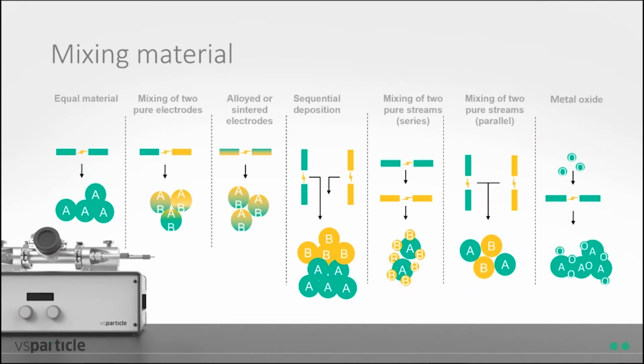Again, there's enormous flexibility also in mixing different compounds. We can use two electrodes of the same material producing the same nanoparticles. We can mix different elements by using two different electrodes. And we can also process sintered or alloyed electrodes, giving us full control of elemental composition in the nanoparticles. And then last, we can play with configurations of multiple nanoparticle generators and make all kinds of compounds. And we can play with gas composition to make oxides or maybe even borides or nitrides.